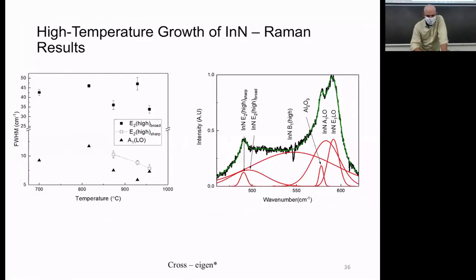Again, if I can get my laser to pop up, there it is. And it comes straight down, and you can see that just gets better every time the temperature goes up. That's a great result, because that means that not only do I have indium growth above my decomposition temperature, but my indium nitride quality is getting better, or at least some of it might be getting better as I get higher temperatures.